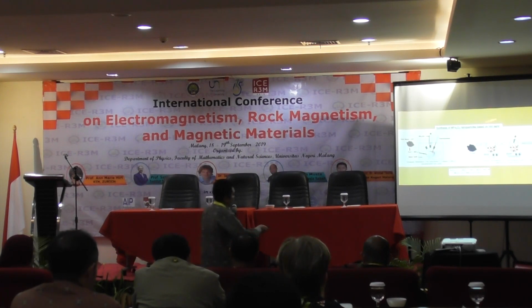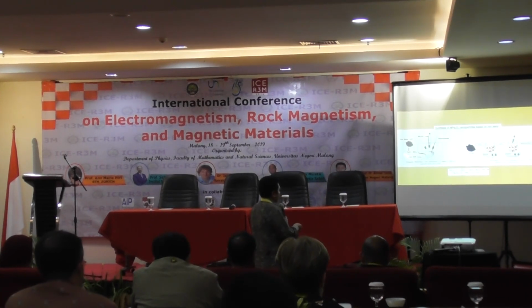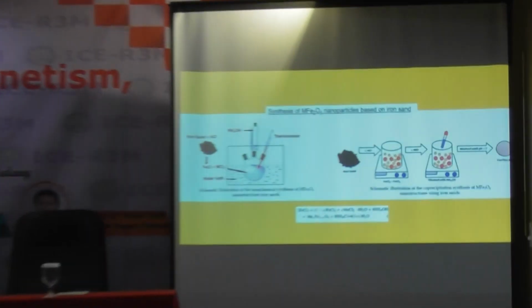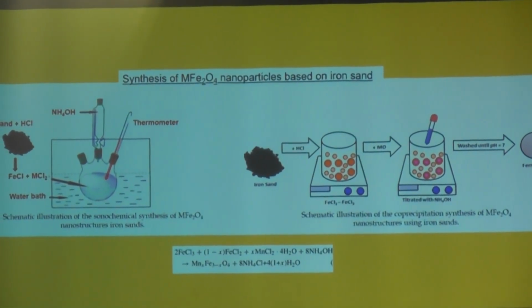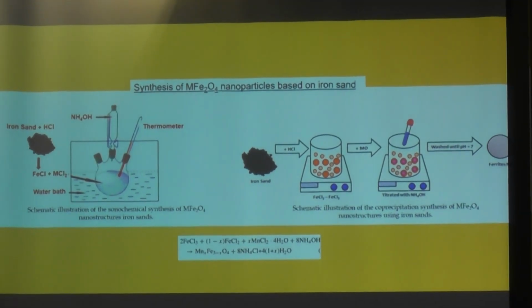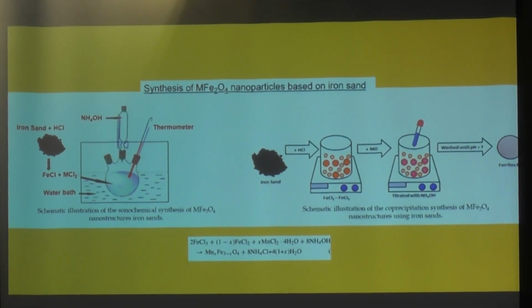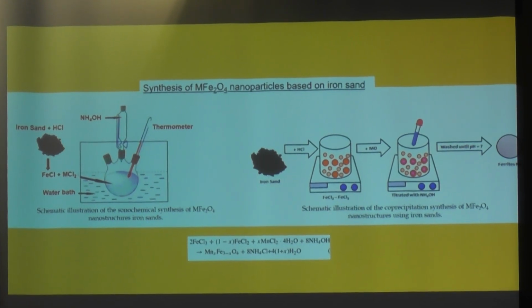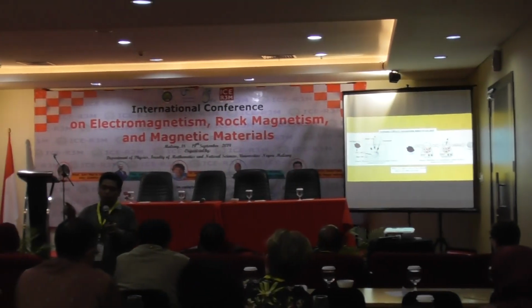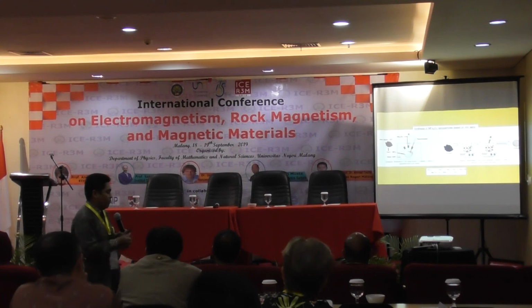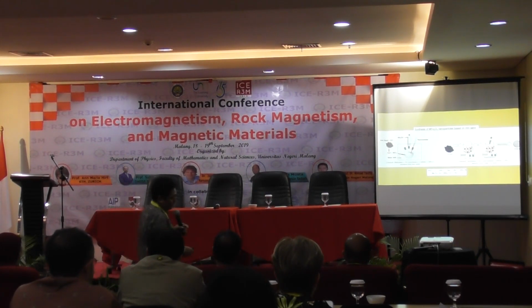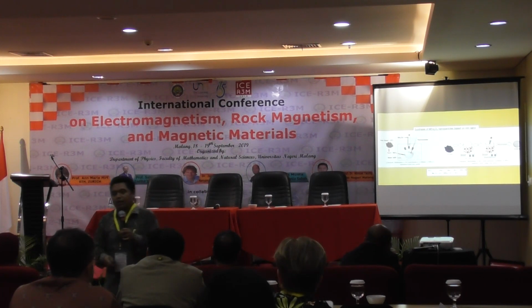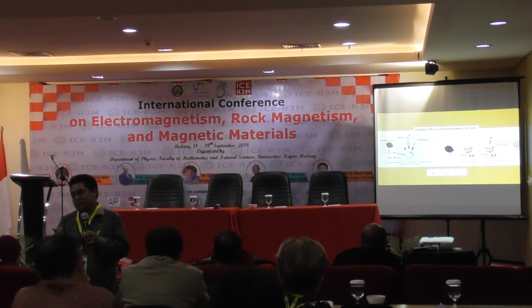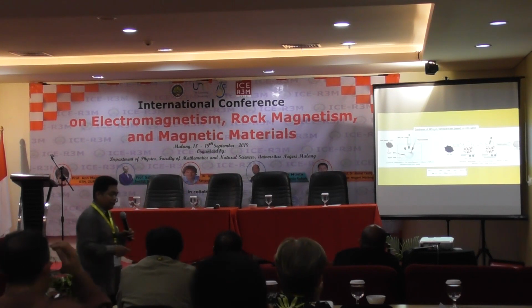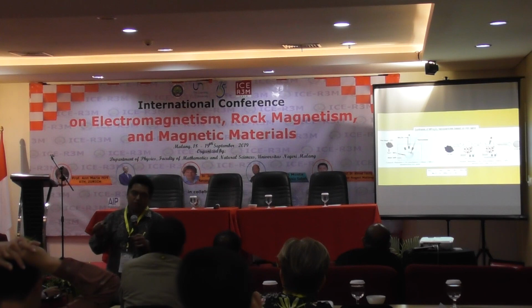Okay, the synthesis that we developed in our laboratory, this iron sand, we know that the iron sand has many impurities, so we extract the iron sands, especially the black iron sand. We know that the black one consists mainly of the compound magnetite, not hematite, not Fe2O3 or FeO, but Fe3O4. We call it magnetite or black iron oxide. So we separate it with physical treatment many times using a permanent magnet, and we can get a powder of iron sand that is almost 100% magnetite, but the particle size is still in micro size.